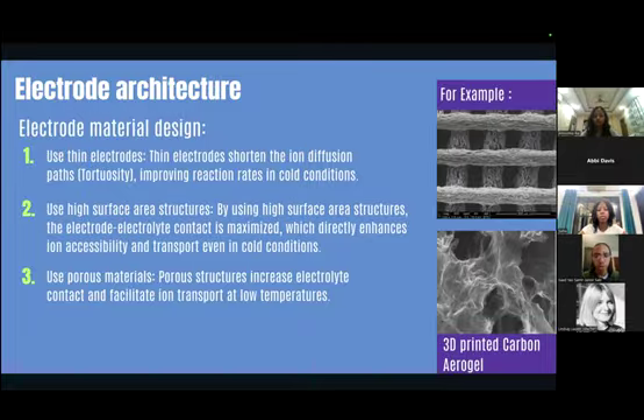slows down ion movement. And third and lastly, porous materials play a vital role. The network of interconnected pores throughout the material creates pathways ranging from nanometers to micrometers in size. And these pores allow electrolyte to penetrate deep into the electrode structure, ensuring ions can access reaction sites throughout the entire material volume, not just the surface. And as an example of a solution, we thought of 3D printed carbon aerogel because it has this porous structure that can easily fit the three elements that I was discussing.